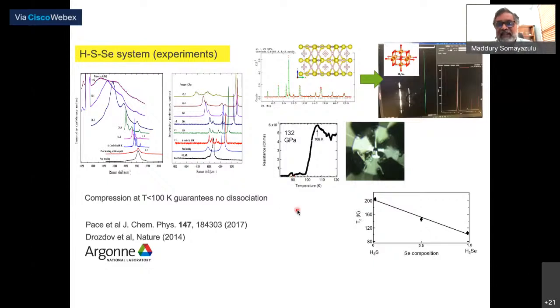I'm just presenting some details from our unpublished data, which I think also corroborates some of the published data which has come out in recent days on the system. We looked at sulfur and hydrogen, which was simple because hydrogen sulfide is something you can load into a diamond cell. Now, what about selenium and hydrogen? Or what about a solid solution of sulfur and selenium in hydrogen? Is it possible to do this? And how does it tune the transition temperature?